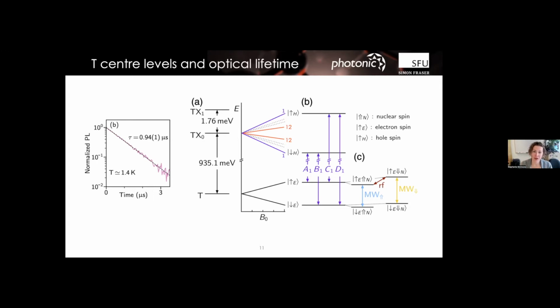So fortunately, the ground state, the electron spin, doesn't seem to care what orientation it's in. It's an isotropic g factor, so that means you have the same kind of Zeeman splitting regardless of which center it is. But the excited state, that hole, cares a lot about what the orientation of the magnetic field is. It's an anisotropic g factor. So basically you have 12 different splittings in the excited state, which means for this pseudo spin 1/2 to spin 1/2, each of which have 4 optical transitions, which you could tap, right? That means you have 4 times 12, 48 optical lines that you're looking at, in an arbitrary ensemble.